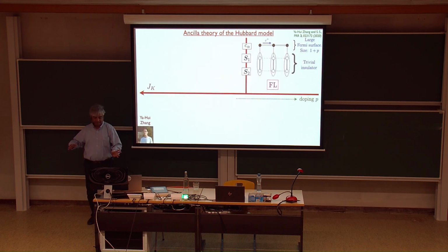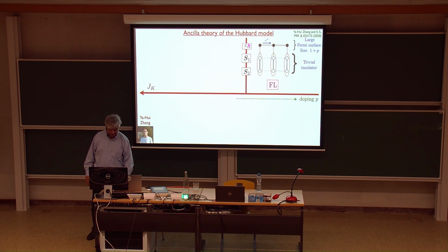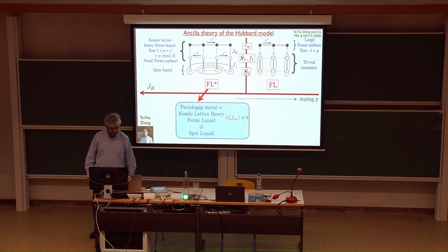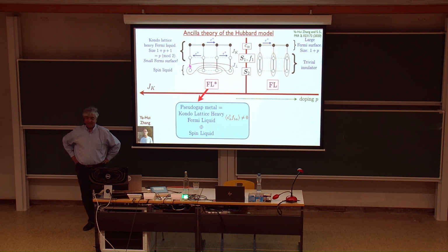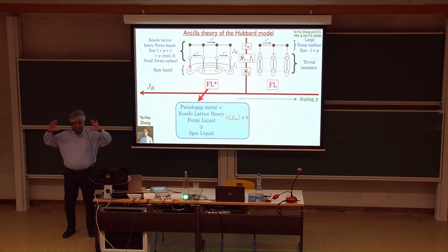So when JK is small, then these two spins will form a singlet, and this will form a Fermi surface of size 1 plus p, which is what you see at large doping. Okay, what happens when JK becomes larger? Which, let's say, is what happens when doping is smaller? Well, the top two layers are just like the Kondo lattice I told you about. And what did I tell you the Kondo lattice, we now understand, likes to do? The Kondo lattice likes to form what I call a large Fermi surface, which counts both the spins and the electrons, F plus C, inside the Kondo lattice.